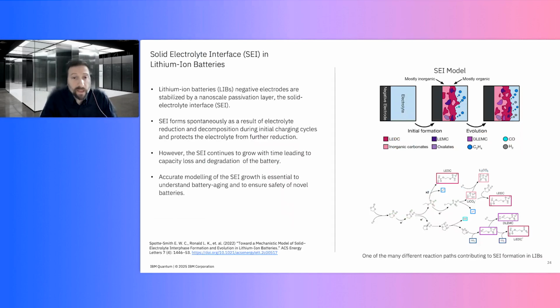And we think there are many problems where we could apply SQD. So one of these problems where we see potential is in the study of the reactions that happen at the solid electrolyte interface of lithium-ion batteries. In lithium-ion batteries, negative electrodes are stabilized by a passivation layer that is called the solid electrolyte interface. And this interface forms spontaneously as a result of the reduction of the electrolyte and its decomposition during the initial charging cycles of the battery, and has the effect of protecting the electrolyte from further reduction.